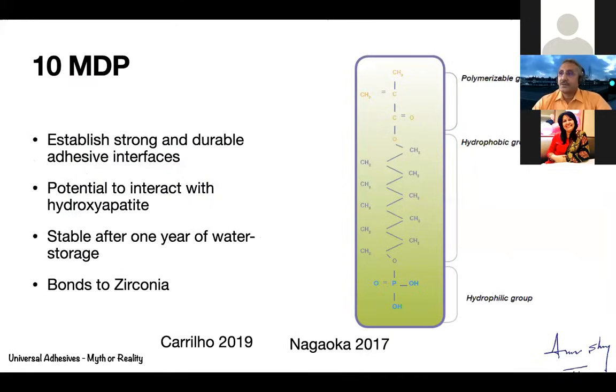Now this is 10 MDP, and again, I'm not going to go too much into the chemistry because we have very limited time. But one of the most important things about it is it has the potential to interact with hydroxyapatite. So there is an adhesion decalcification concept. Depending on the pH of an acid, like say if you take phosphoric acid on one side and 10 MDP on the other, both of them have a phosphate radical which is going to attack the hydroxyapatite, leading to calcium release, and then the phosphate in these radicals will combine with the calcium to form a calcium phosphate salt. Now this happens with both phosphoric acid as well as with 10 MDP.